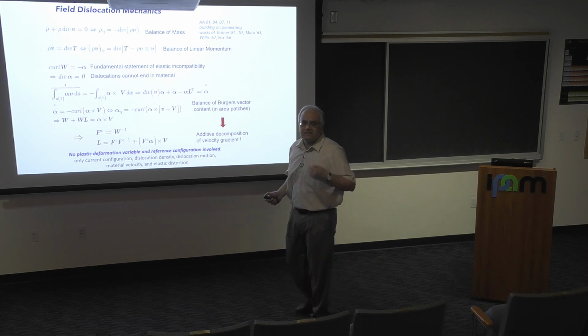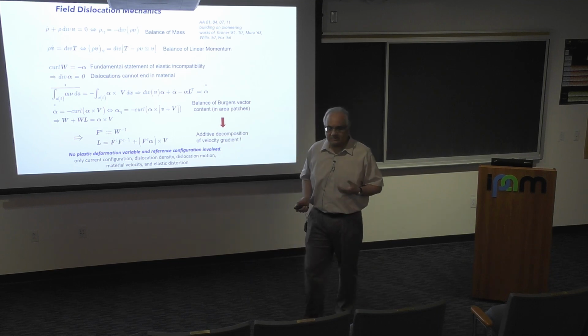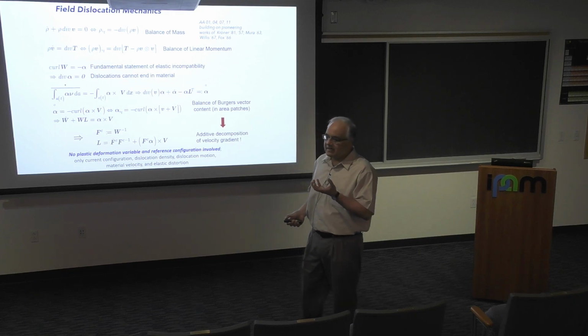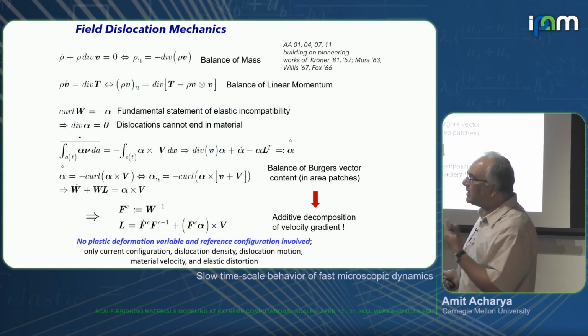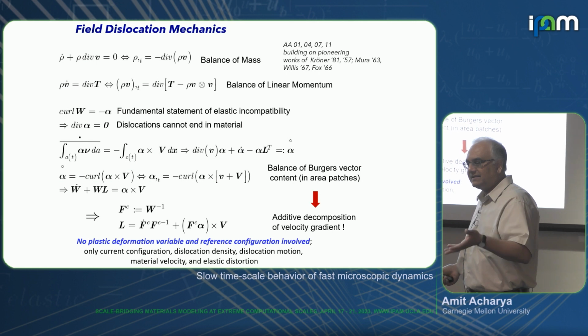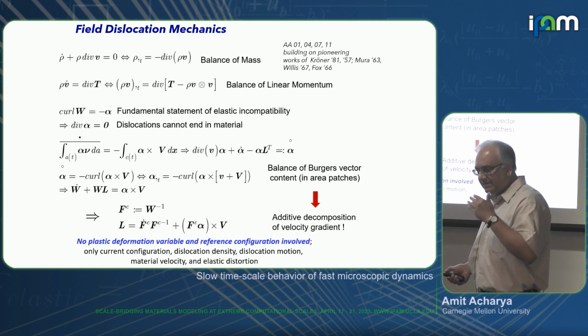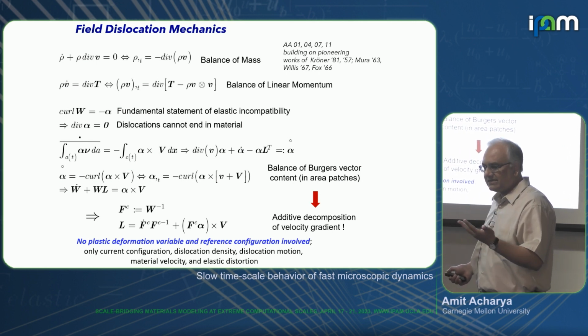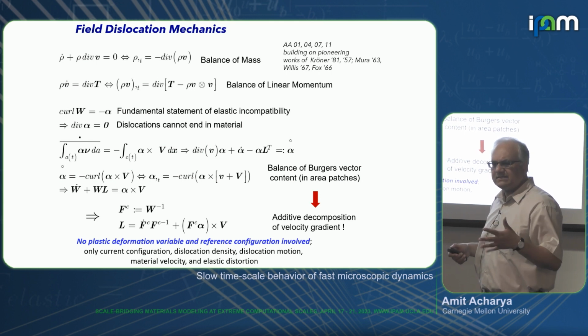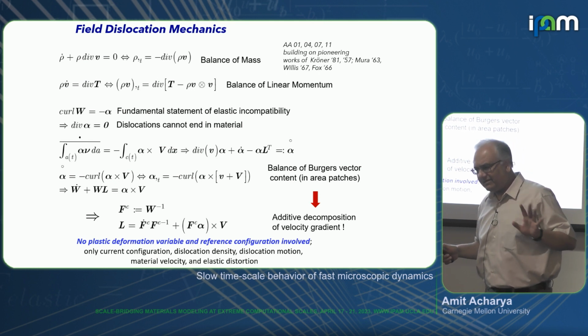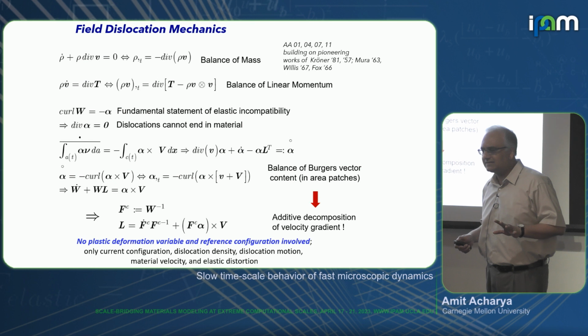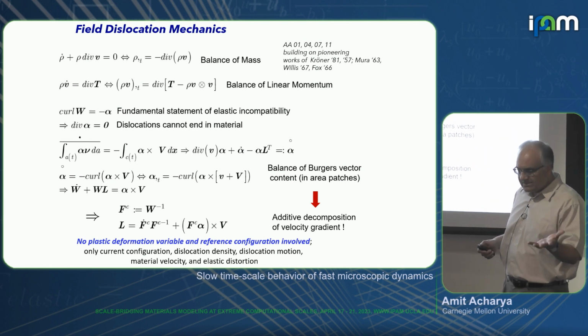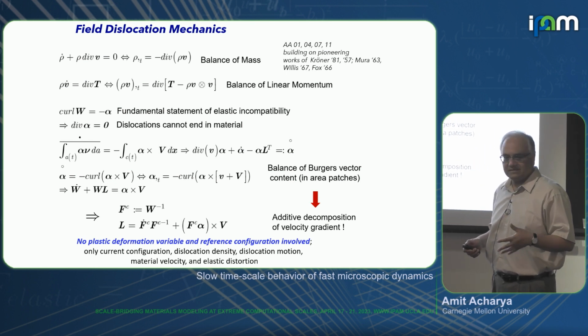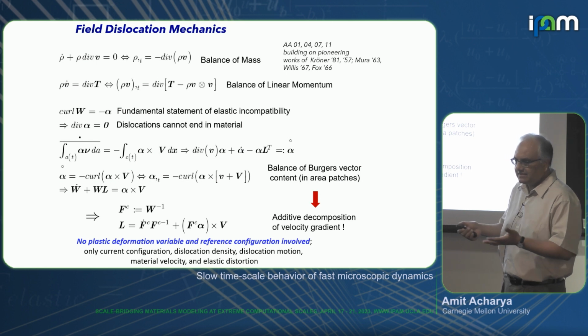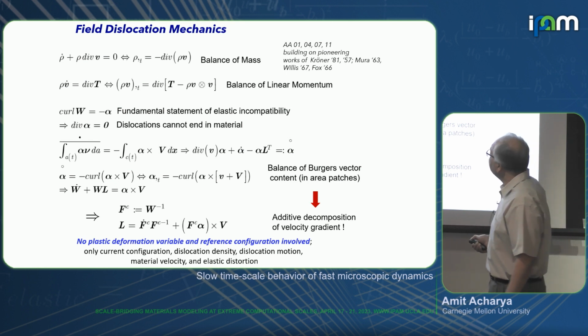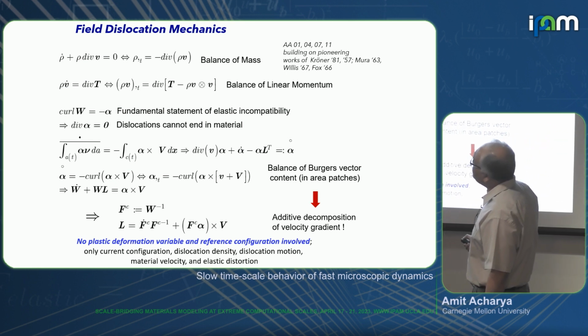And the difference between elasticity and here is that in elasticity, the deformation gradient, as you know, we'll work with the inverse deformation gradient, okay? Not the deformation gradient, but the inverse elastic distortion. There are good reasons. When you do plasticity, you don't want to involve a reference. There are very good reasons for doing this, because there is no distinguished reference, and you can't observe things other than what's available to you. So this is the inverse elastic distortion.